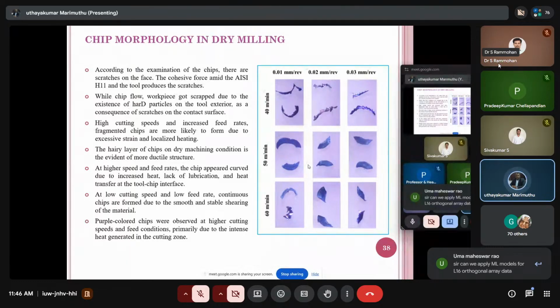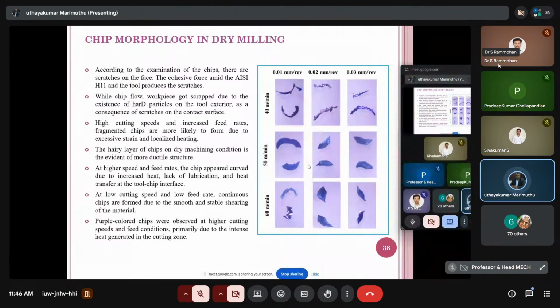Then you can see at higher speed and feed rate, the chip appeared curved due to increased heat, lack of lubricant, and heat transfer at the tool-chip interface. At low cutting speed and low feed rate, continuous chips are formed due to smooth and stable shearing of material. Right? You can see the first one, that is a serrated one.